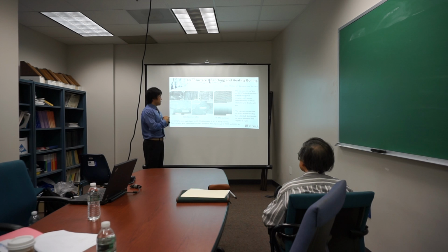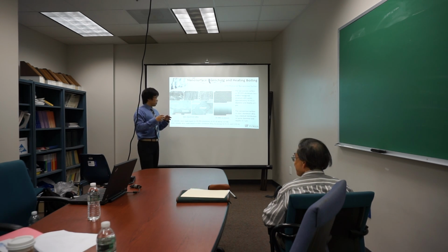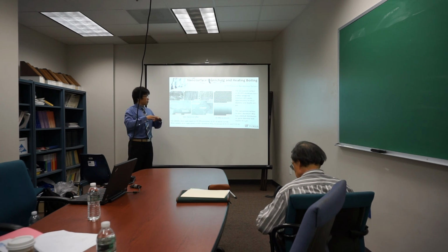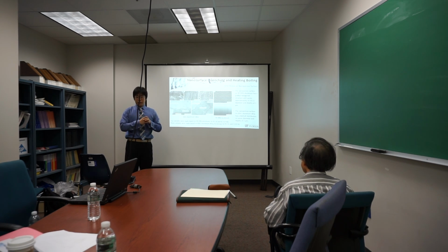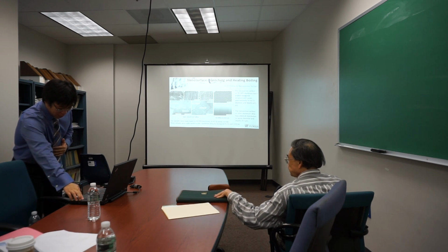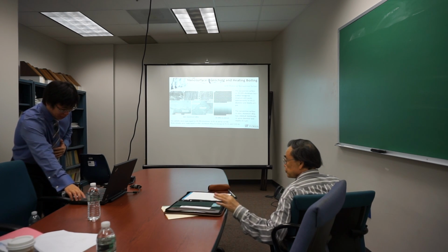And on the right-hand side, there are two figures. The first one is pure aluminum, 30 minutes, where the holes are very well aligned with each other and almost have the same diameter, which is about 50 nanometers, and the depth is 5 microns. But for the aluminum alloy, all of the depths are about 2 microns. So please remember these parameters, and we're going to see that one later.